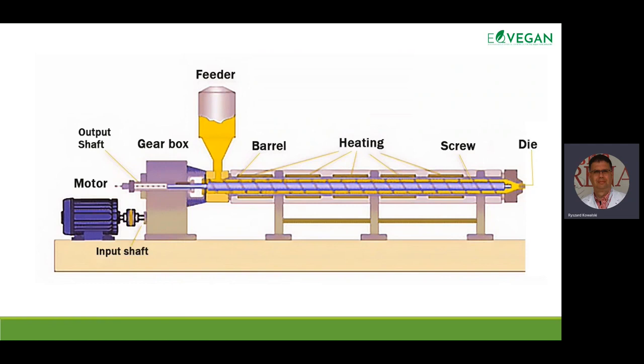Flavorants, coloring agents, and other liquid additives may be introduced at this phase of the process to ensure thorough mixing of all the foodstuffs entering the extruder barrel. Extrusion processes that do not utilize an effective preconditioner often operate at lower capacities and require a larger main drive motor for the extruder and a longer length to diameter ratio to create comparable texture.